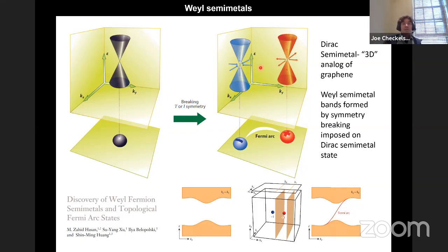And these 2 Weyl cones themselves, then, for example, in the bulk are interesting. There's Berry curvature associated with those points in momentum space. But perhaps even more interestingly, when you go to the physical boundary of those systems, they also have a kind of topological feature, but it comes in the form of the so-called Fermi arc, which connects those points in k-space. So it's a very different animal than the original topological insulator. First of all, even in the bulk, there are interesting modes, which are really sourced near these momentum space points. But then at the surface, they terminate in these beautiful Fermi arcs.